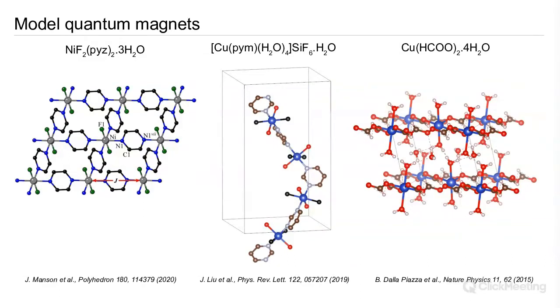This is with copper bonded by pyrimidine, and then on the right here I just give another example, copper formate tetrahydrate, and this is one of the most two-dimensional materials, arguably, that's known in terms of magnetic ordering, by virtue of the fact that the magnetic exchange is almost negligible through these hydrogen bonds between the waters, between the planes. And this is a beautiful example of a two-dimensional magnetic system where there have been observed fractional excitations, if you like, the 2D analog of spinons that are found in 1D chains. So there's lots of interesting aspects of these systems from a magnetism point of view.